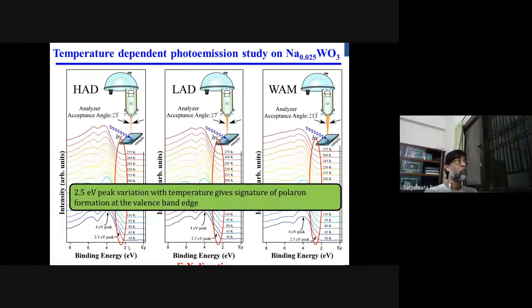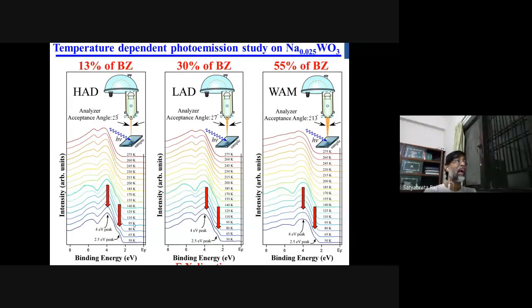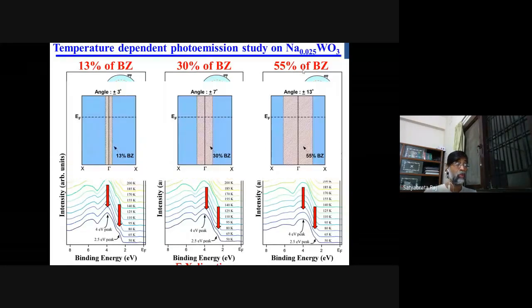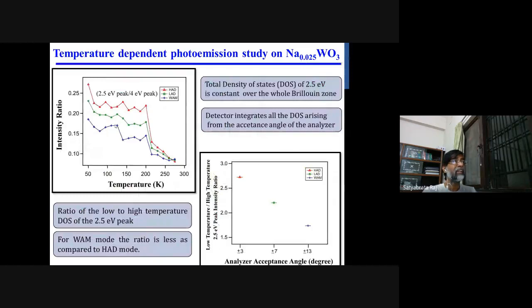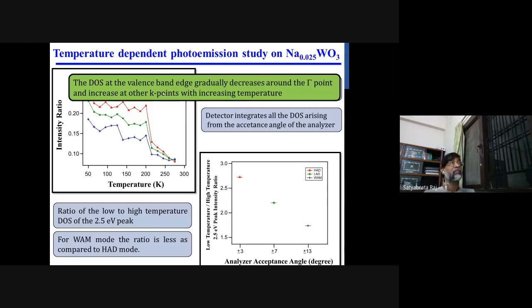So the 2.5 eV peak variation with temperature gives the signature of polaron formation at the valence band edge, and this is for 13% Brillouin zone integration, whereas the others are for 30% and 55% of the Brillouin zone. A wider integration gives no variation of the density of states over temperature, whereas a 13% Brillouin zone integration gives a high density of states difference between high and low temperature. So we conclude that the density of states at the valence band gradually decreases around the gamma point and increases at other k points with increasing temperature.